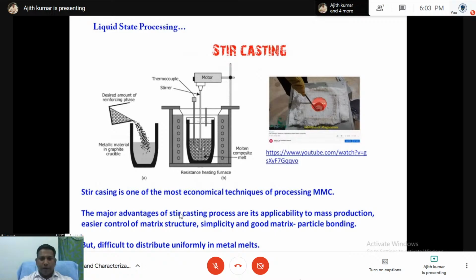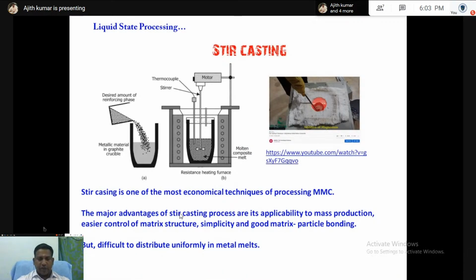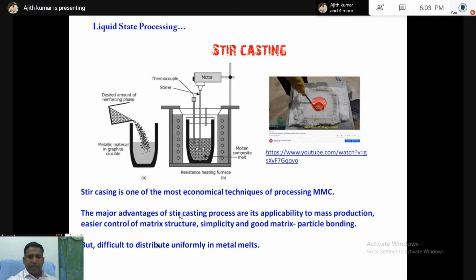We have a crucible. In the crucible, we melt the material like aluminum, magnesium, any metal. We melt it above its melting temperature. Then for the mechanical stirring, we put in a stirrer with a motor, at about 1000 to 1500 rpm. If you stir it, we can get a vortex. In the vortex, if you put some ceramic particles, they will mix homogeneously, though some heterogeneous mixture may come into the picture. Then, if you pour it into the mold, we can get the composite.